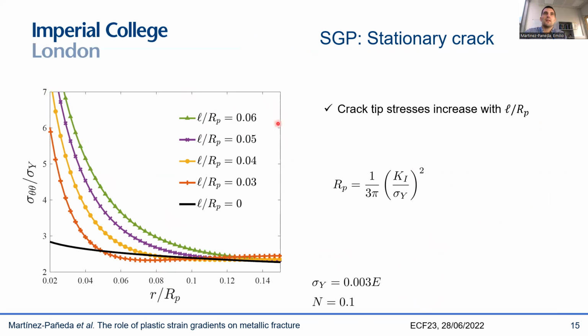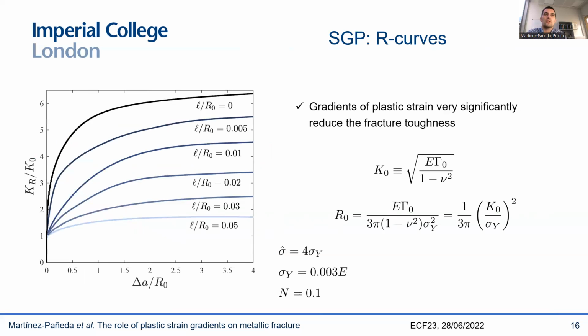And as you would expect, the higher the value of this ratio, the easier it is for a given load for the material to harden, to exhibit an elevation in stresses associated with these GNDs. So this is all in agreement with expectations. And then we model this crack propagation curve, so this R curve.